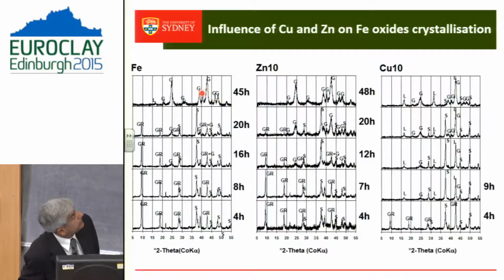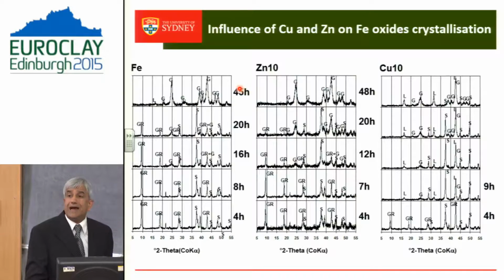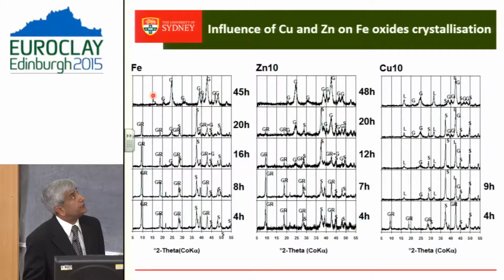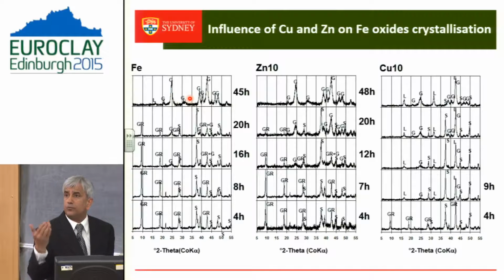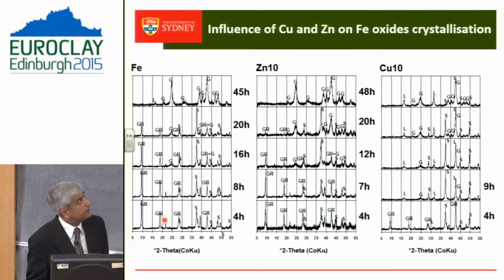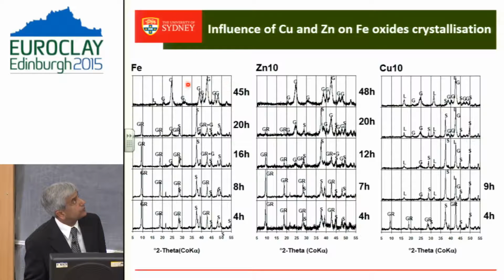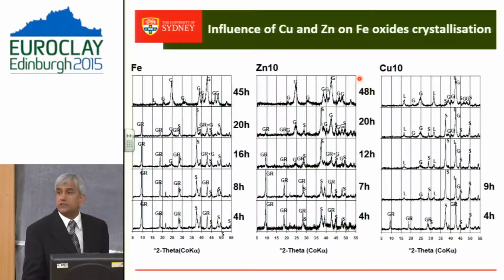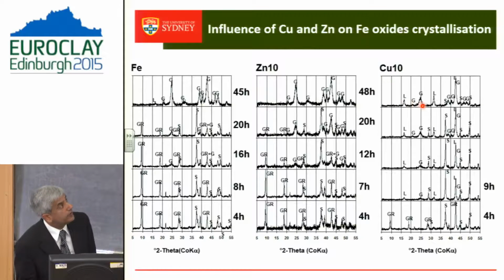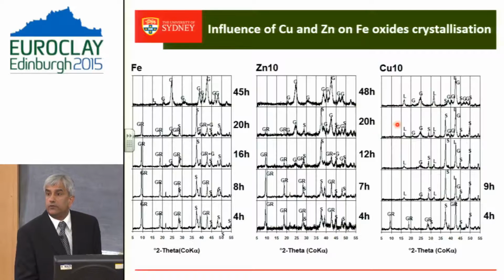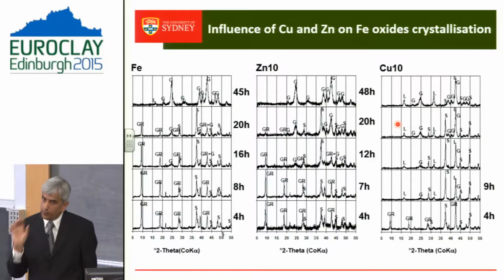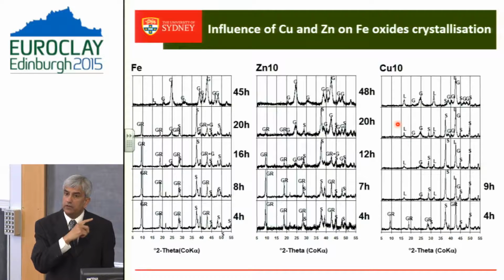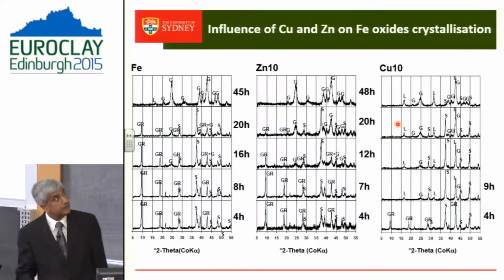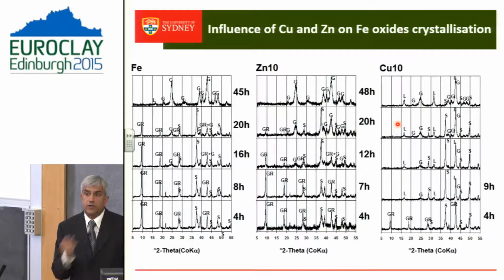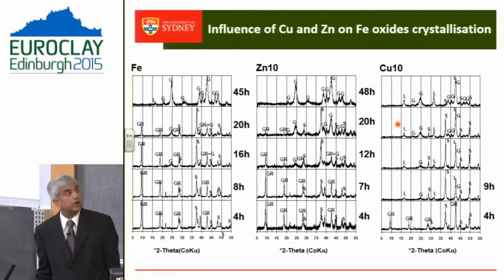I don't want you to read any of these in detail, but after about 48 hours, this is the pure system. You got almost everything formed into goethite; it started with a lot of siderite and other things, but we have got more or less pure goethite. Similarly, in the presence of zinc, we are able to get goethite. However, when you look at the system with copper, you can see there is a fair amount of lepidocrocite in the system. So what we are seeing here is that when you have copper present in the system, goethite formation, once again, as we saw earlier, copper interferes with the crystallization of goethite, and here lepidocrocite is preferred in the presence of copper.